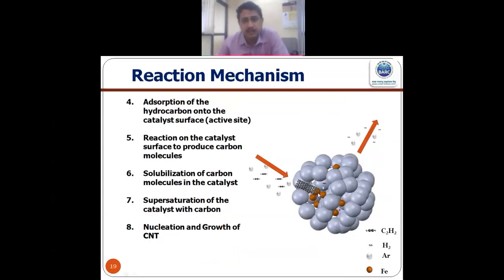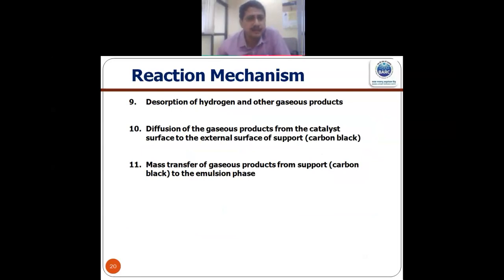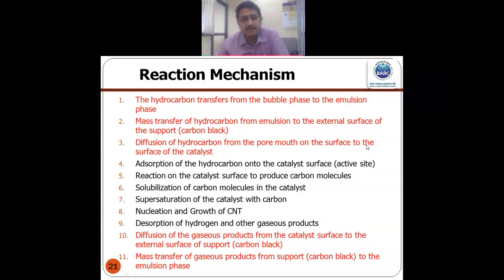And once they come to the iron nanoparticle, the hydrocarbon gets adsorbed on the iron nanoparticle. Then there will be reaction. Acetylene gets dissociated, carbon molecules are formed, and these carbon molecules get solubilized into the catalyst particle. Initially saturation happens, then supersaturation happens, and from supersaturation carbon nanotubes come out, and the hydrogen gas and other byproducts come out in the gas phase, and carbon nanotubes start rolling. The other steps are again the reverse of that, that is the desorption of the hydrogen and other gaseous products, the diffusion of the gaseous products from the catalyst surface to the external surface of the support, and finally the mass transfer.